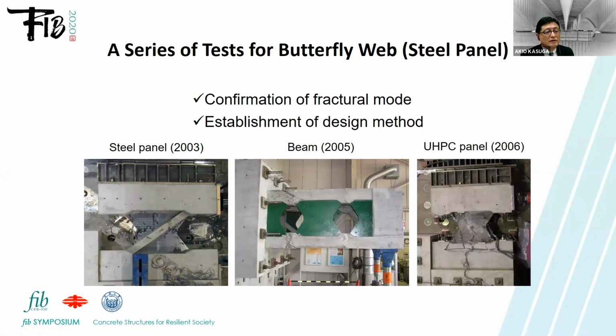After the concept of the butterfly web, at that time, the first time the panel was steel. I presented in the paper 2006 in April Congress. At that time, the butterfly was steel. We did the test in 2003, and then we did a beam test in 2005. It's also the steel plate. But in 2006, we did the concrete panel. And also I presented in 2010 FIB Congress in Washington, D.C. At that time, UHPC is available for the practical field. We checked the same things as a steel panel.